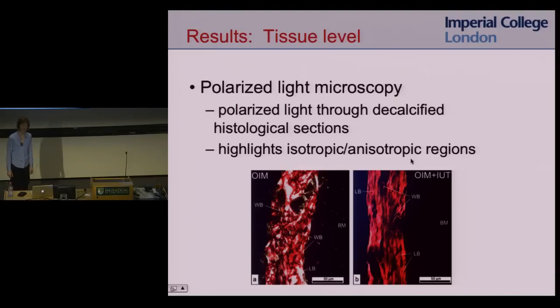So we wanted to look at the collagen. What's different in the collagen? Well, what's interesting at the tissue level is the arrangement of the collagen. In a normal bone, the collagen is very arranged and structured, and that's what gives the bone the tensile strength. So one way we can look at the arrangement of the collagen is using polarized light microscopy. So we took decalcified sections of bone, shone polarized light through it, and the polarized light highlights the isotropic and anisotropic regions. So you can see, this is the OI bone, and this is the stem cell treated bone. The collagen looks a lot more organized in the stem cell treated bone than in the OI bone.